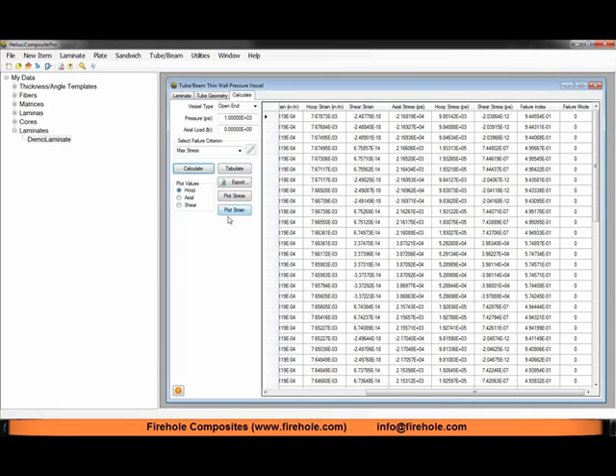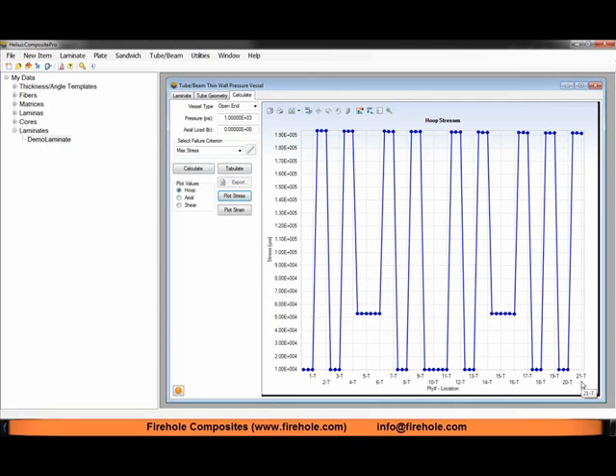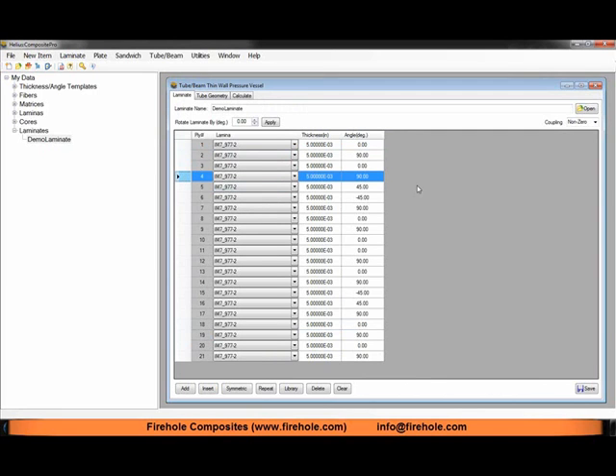We also have the ability to plot these stresses and strain in the hoop axial or shear direction. I can plot my hoop stresses by selecting the hoop radio button and plot stress. Then I get a plot of all these stresses at all my composite points. There's three points, bottom, middle, top for each ply for all 21 plies. You can see my highest stresses occur in my plies 2 and 4. If we go back to our laminate tab, those are our hoop wound plies. We expect in an open end internal pressurized composite vessel to have the hoop plies take the majority of the load.